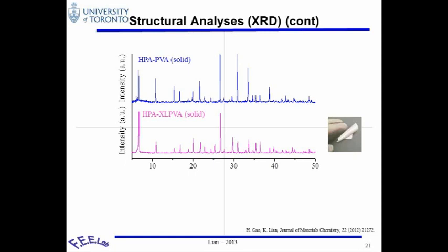And what we want to look for is a few characteristic peaks here that correspond to hydration, which is right here, and dehydration, which is this peak, and also we were looking at the Keggin structure to make sure that we are using the HPA, which is still in the Keggin structure range.